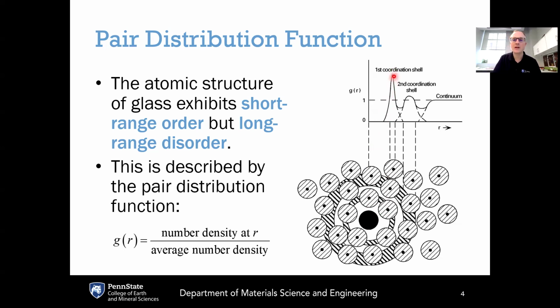Now, the fact that this peak is going well above 1 means that the number density at that first nearest neighbor distance is much greater than the average number density in the limit of a large distance. So what this means is that you're much more probable to find atoms here in this first coordination shell compared to just some random distribution of atoms. And if you look at the structure, indeed, that's what you see, that if you move out radially from the central atom, the first nearest neighbors can be found at a fairly well-defined distance out from that central atom.